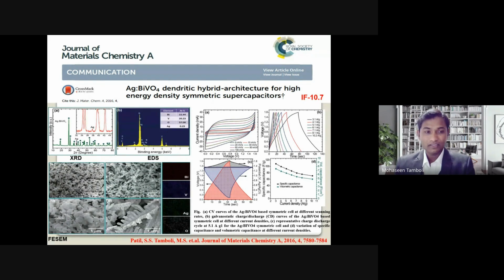You can see the figure of the XRD pattern. There is a BiVO4 peak, but there is a low concentration of silver, so we cannot see the exact peak, but when we go for the EDS, it shows the silver is present there. And you can see the FESEM images, which show the dendrite-like structure of BiVO4. When we add the silver there, some agglomeration can occur after the addition of the silver. And the elemental mapping also shows that all the elements are present here.